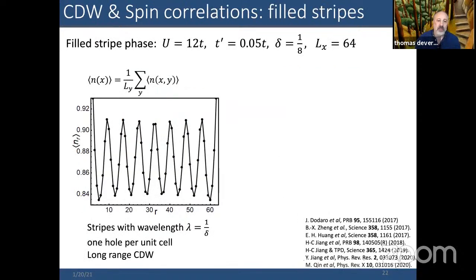And so if you plot, here are some results. I'm going to highlight these papers that I list down at the bottom here and just show you the plot of the density here on the left-hand side. Electron density as a function of position, and look at first the case when T prime can be set to roughly zero, and U on the order of 12 T, and this is at a doping of 1/8. So there's very clear modulation in the charge density, and the period of the charge density is just period eight. It's set by the 1/doping.